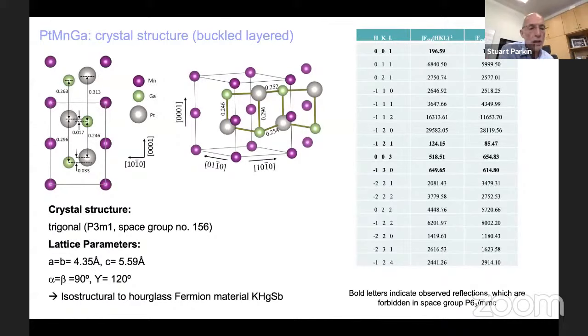It's not a Heusler compound. It has a trigonal structure. And the structure we've discovered is non-centrosymmetric. And therefore, you actually have an ordered arrangement of platinum, manganese, and gallium.